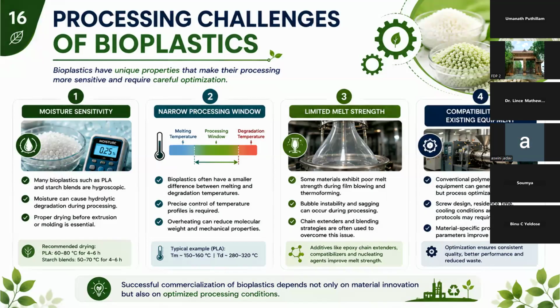moisture in it, and also the narrow processing window. As I mentioned, it is the melting temperature, processing window, and degradation temperature. So the films or the pellets have to stay a very short time in the extruder. If it is exposed for more time, it will be degraded. Limited melt strength is another parameter, and the compatibility with existing equipment.